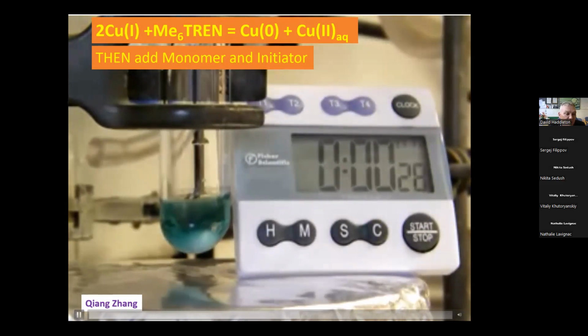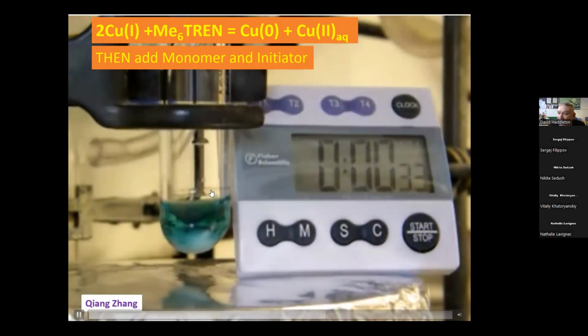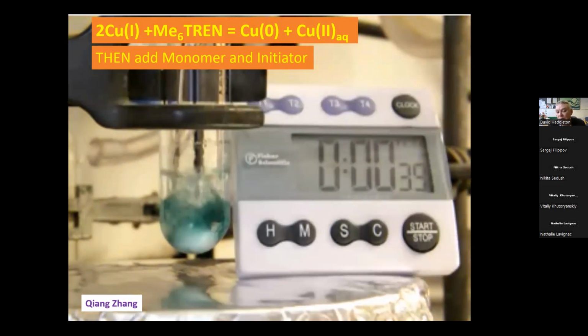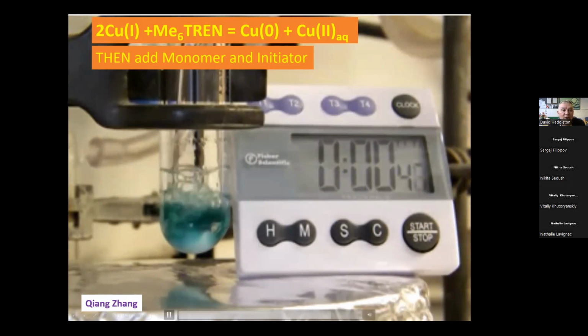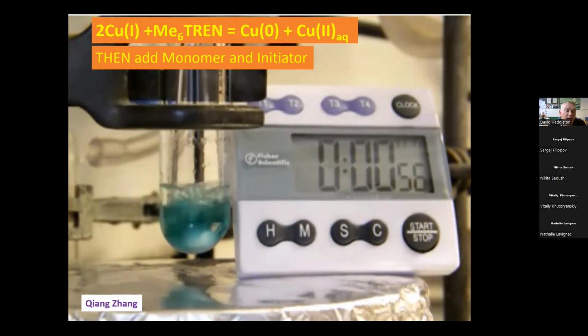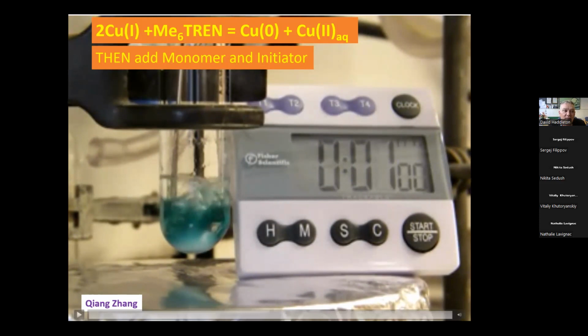And if you look at these bits of black stuff, I'm not sure at the top, that it's copper 0. At the time, we thought you had to degas. You actually don't need to degas. But here we're just bubbling with some nitrogen to make sure there's no oxygen in there. And I'll come on to the next slide on why you don't need to deoxygenate. And then once we've done that, we have no copper 1 left. It's just copper 0 and copper 2. We then add the monomer